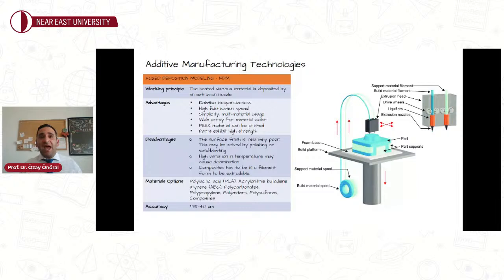The molten viscosity has to be high enough to give structural support during the fabrication, but also low enough to allow the extrusion. You remember that nozzle clogging cannot be encountered in SLA technology. But this is a nozzle-based technology, and this can cause nozzle clogging. That's why the temperature of the molten thermoplastic material should be appropriate to support the structure and also not cause a clogging effect, unfortunately. Multiple nozzles are available in contemporary dentistry. You can print with multiple nozzles and also with multiple colors.